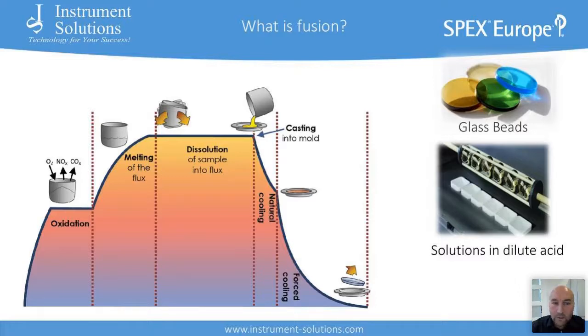Then we will do the oxidation of the sample at a temperature below the melting point of the flux. When the sample is oxidized, we will move the temperature to the melting point of the flux. Then the sample starts dissolving. We help the dissolving by rocking the crucible. When the sample is completely dissolved, we can cast the molten flux with the dissolved sample into a platinum mold. The result is then a glass bead that can be analyzed in an XRF system.